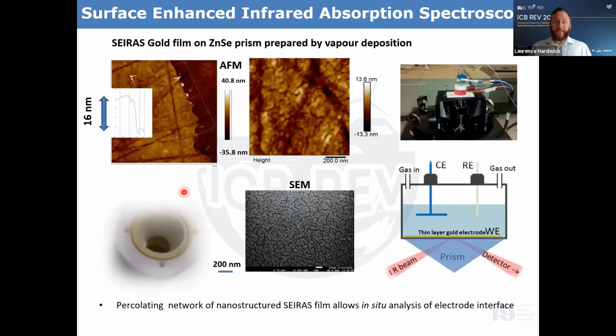Okay, so I'm going to now finish by highlighting some of our work on SEIRAS, our surface enhanced infrared absorption spectroscopy. What we're able to do is get much more specific information on the electrochemistry that's happening at the electrode surface. On a prism, here silicon or zinc selenide, we evaporate a very thin gold layer, and it has this sort of nanostructure. On the surface is a percolating network of gold about 16 to 20 nanometers thick, and this is our working electrode. So why do we do this in this configuration?